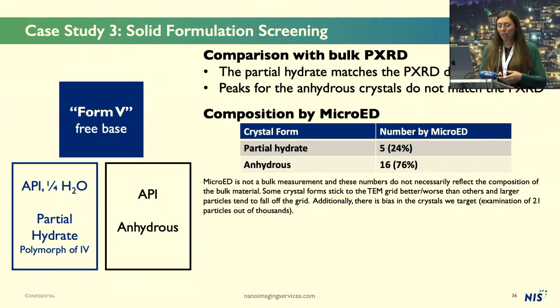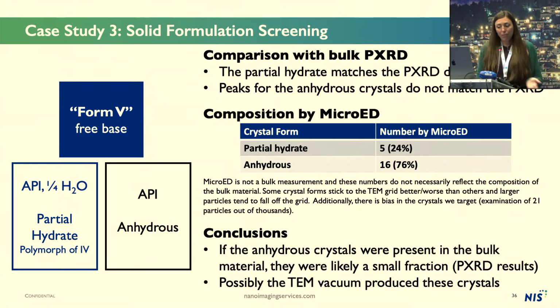Also, with the preparation of that grid, some particles stick to the grid material better than others, and so there can be bias in that. And then also large particles tend to fall off the grid. So there's definitely bias, and in other experiments we've shown that there is bias in what we see in the microscope and what's really in the bulk. So it's always nice to have that measured powder diffraction to go back to, to say what was in the bulk powder. And so from this we concluded that if there were these anhydrous crystals in the bulk material, they were probably a very small fraction, and we're just seeing a small fraction that happened to stick to the grid better for whatever reason. Or it's also always possible that the TEM vacuum dehydrated these crystals and induced the formation of these crystals.